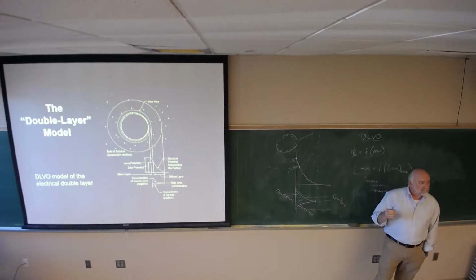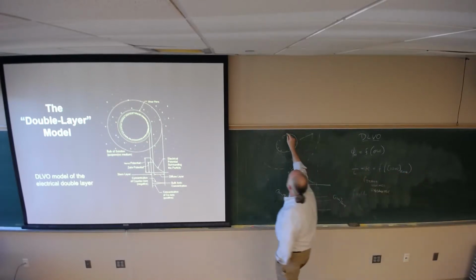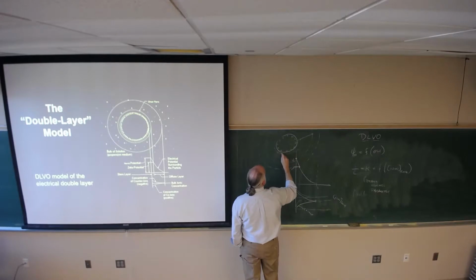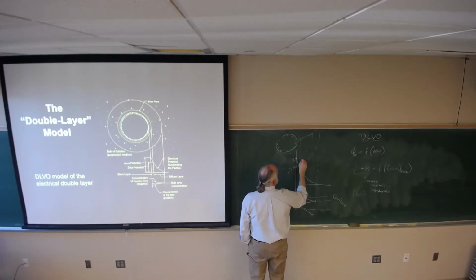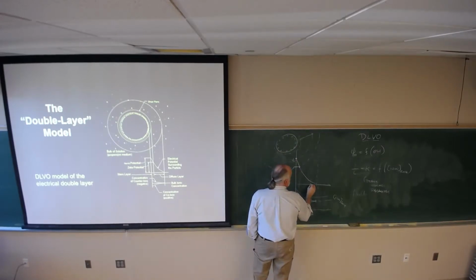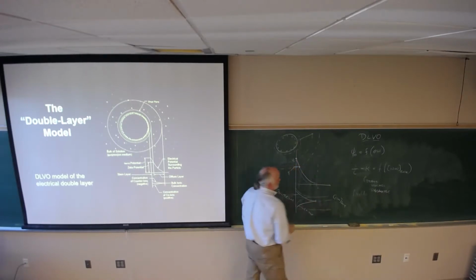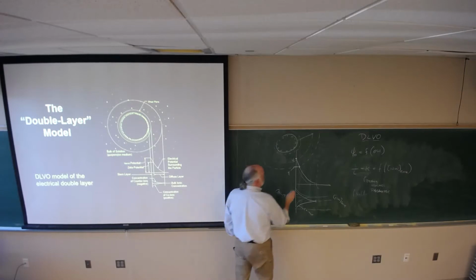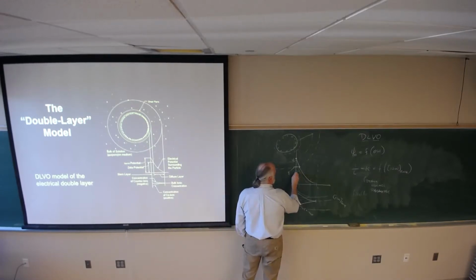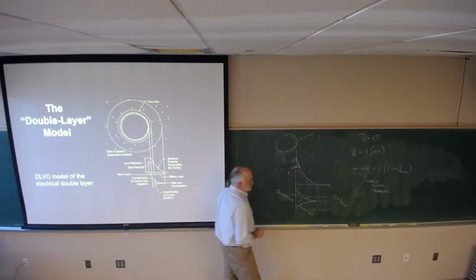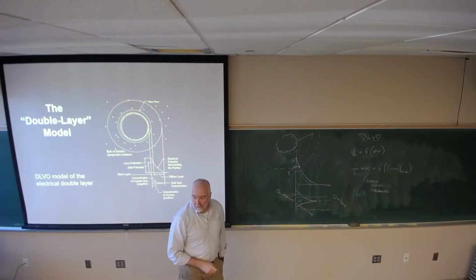Say again. That should also stay the same. It stays the same, right? It's just 3 ion layers absorbed on the surface of the particle. So this stays the same. Okay? But my decay now ends here. So my decay decreases. So what you get is a decrease in the zeta potential by increasing the bulk ionic concentration.